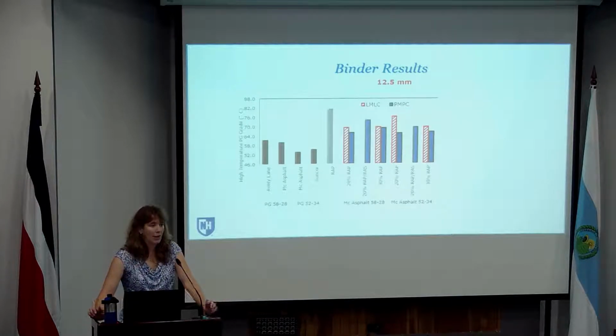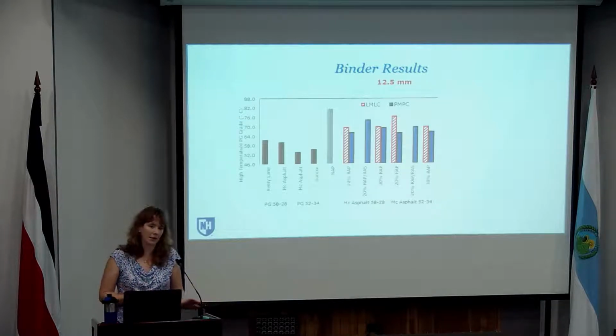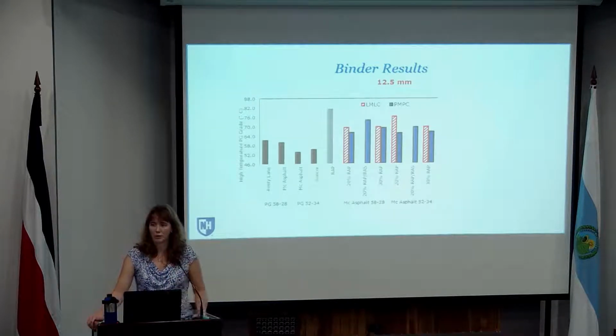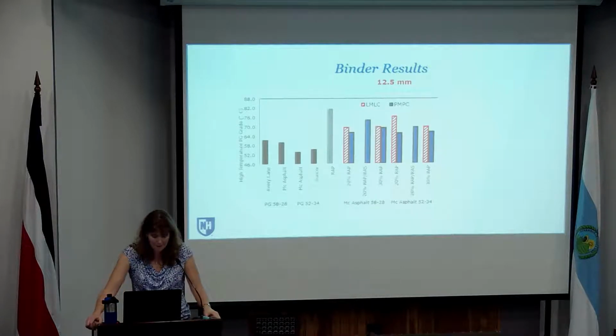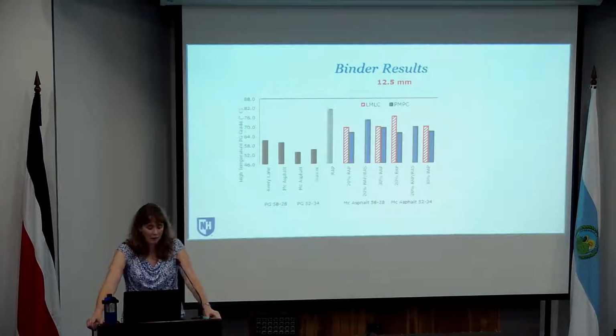When we fabricated the laboratory specimens, we replicated the plant-produced gradation. So it wasn't the mix design gradation, it was the plant-produced gradation. So we replicated what the plant actually produced as close as possible. So really what we're trying to do is isolate the differences in the conditioning that each of the different types of mixtures experienced. So you can see the 2 different binder sources.